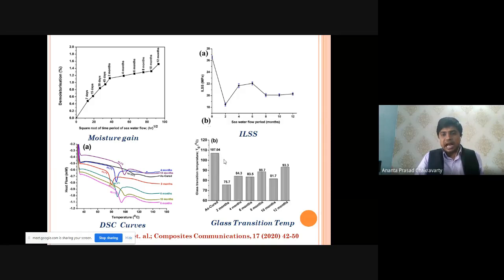And its glass transition temperature, see, it has an approximately increasing trend from 2 months to 12 months. See, 75.7 to 93.3, it is improved. That means its thermal properties also improved. Now, why is it improved? Generally, in moisture, properties should decrease, but here it is improved, in a very slow, continuous manner. That is known as a very low quantitative aspect.